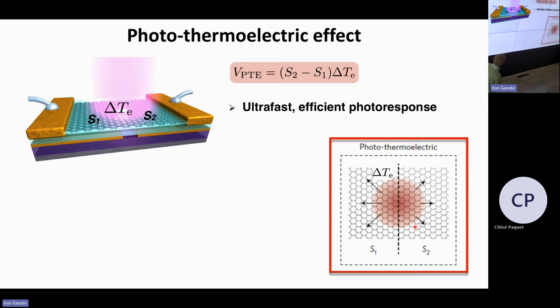Now, you can also use this material to study more fundamental properties. And for that, you can use this photo response, which is also used for several of these applications that I was showing before. And the way this works is actually the photothermoelectric effect. So you have a sheet of graphene. Sorry, it's here. You have two different gates below it where you apply a different voltage. So you have a different Seebeck coefficient on the different parts of the channel, and you shine light, that creates this hot electron state, this higher electron temperature. And then what you have is that you get a local voltage that is created here at this junction.